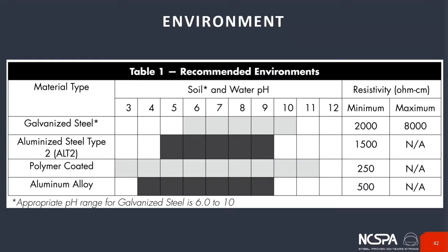Now, what we've done and what this chart illustrates are the minimum and maximum levels for each of the primary coatings as recommended. So as you can see here, galvanized, the min and max soil and water pH are 6 through 10. And the minimum and maximum resistivity is 2,000 to 8,000. Now, the maximum is really going to depend on whether or not you have soft water present. So we don't talk about this very much, but when soft water is present, it has a significantly deleterious effect on the galvanized, and aluminized would be certainly the required or the recommended coating in that instance.